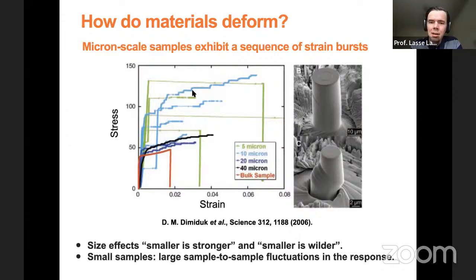So if you have a very broad distribution of these strain bursts, then you can say, okay, your process is wild in some sense. While if you increase the system size towards the bulk sample, these fluctuations actually gradually disappear and you end up having a smooth stress strain curve in the bulk limit, so in the limit of a macroscopic sample. But this is the experimental phenomenology.